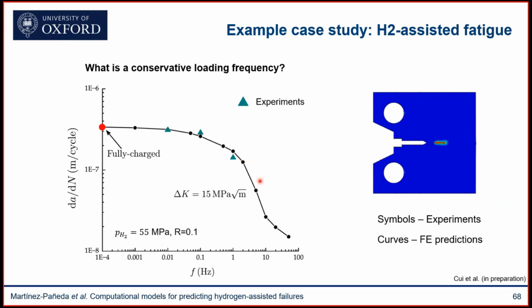For us, because it shows that our model is robust and continues to be robust in predicting experimental responses. But also for the experimentalists, because it means that maybe those things that they were worried about, like leaks, are not really playing a big role. But the other piece of good news is that we see that in this limiting case, it's again not too far away from those crack growth predictions that you get at 1 hertz for this particular material. So again, it could be that they're running the experiments, they're not being non-conservative, but they're running experiments in a scenario that is sufficiently close to reality.